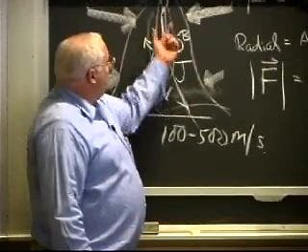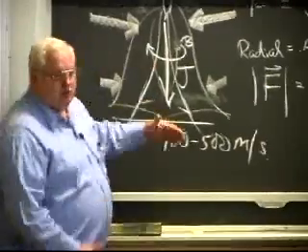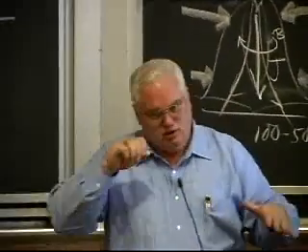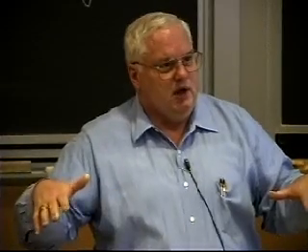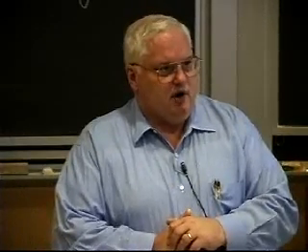because it's a question of the strength of the plasma jet being proportional to how much it diverges. The pressure differential, okay, you get a greater pressure differential if you get more divergence to the current. And by changing some of these easily ionized elements, you can change the rate at which the arc spreads out. You can change the width of the bell, if you will. And changing that can significantly change the stiffness of the arc.